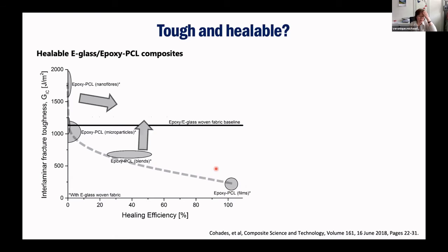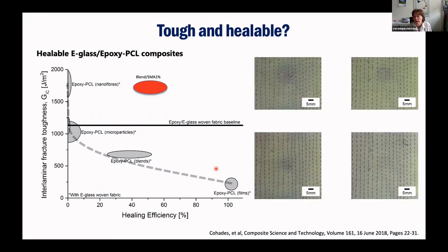So how to get out of this line? We tried to see what we can do. One idea that we had, since we like to use shape memory alloys in our lab, was to put a bit of stitches across the composite. And so we took a sewing machine, and then we took 150 micron diameter shape memory alloy wires. We just stitched them through, and then we did some impact testing, recovery after impact, and so on, DCB.